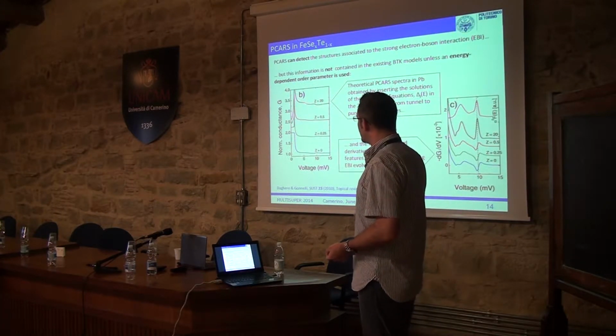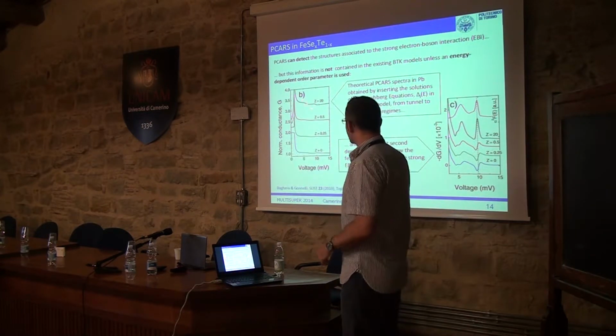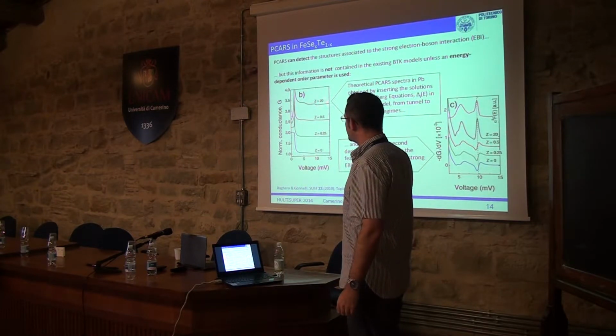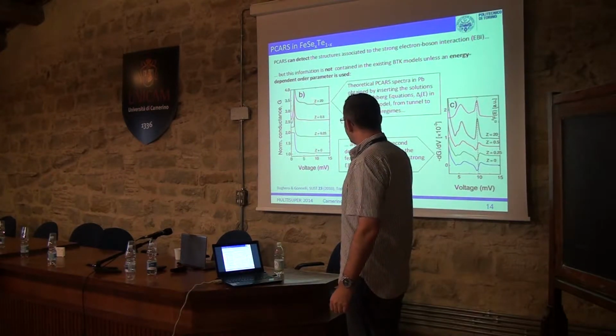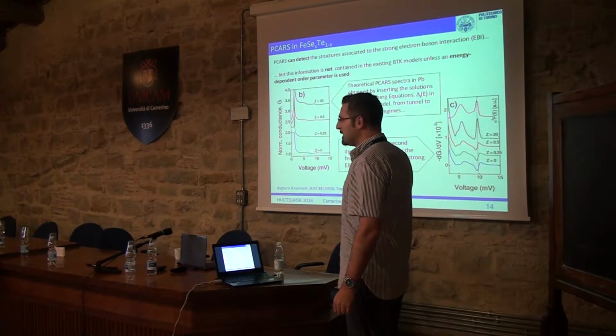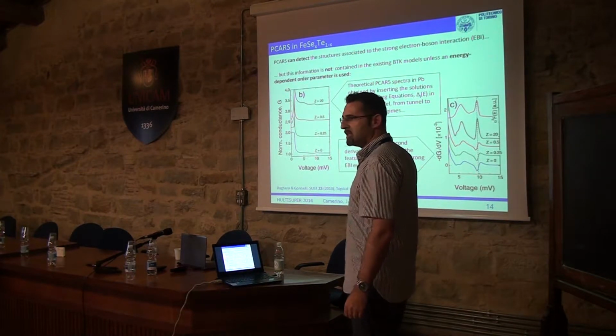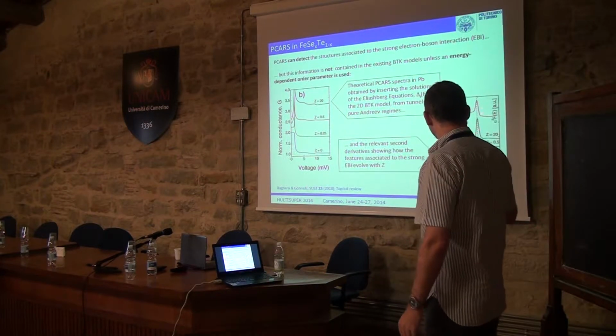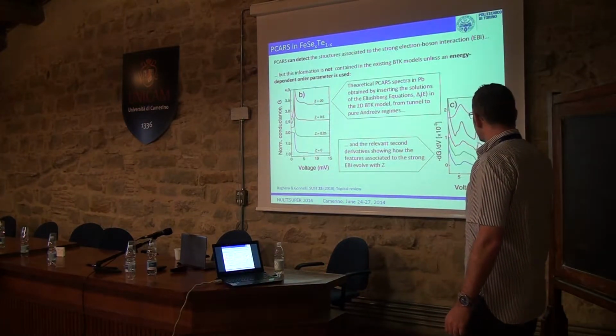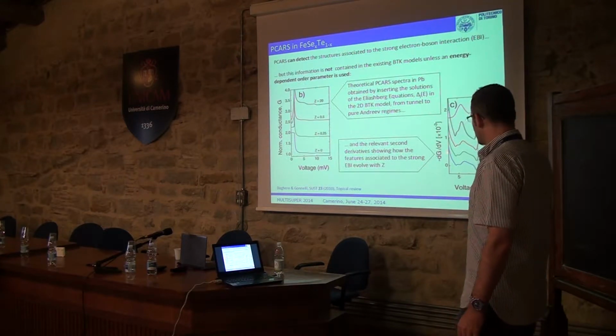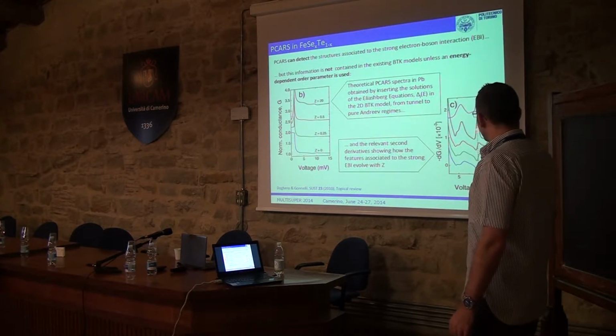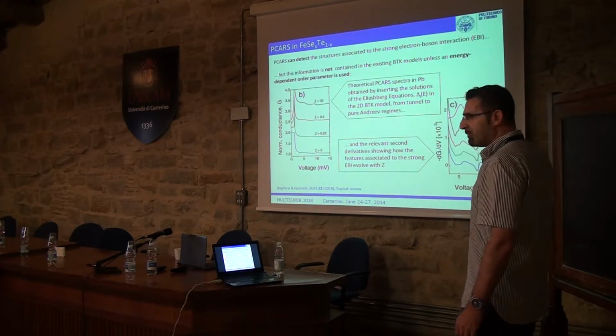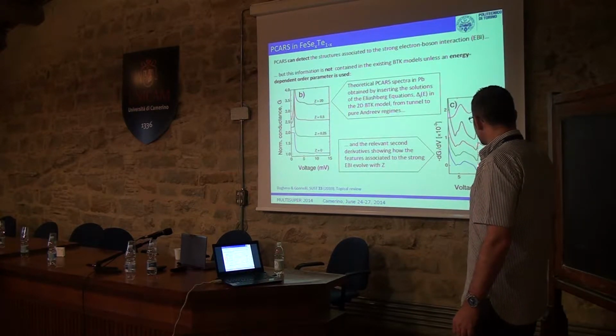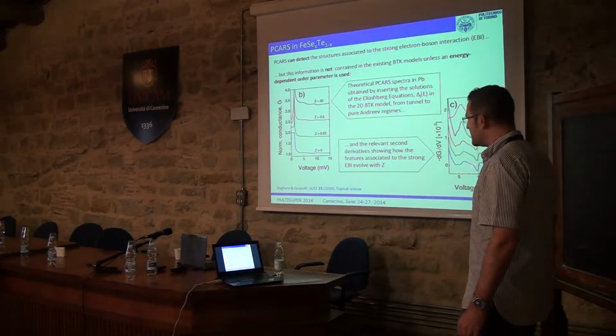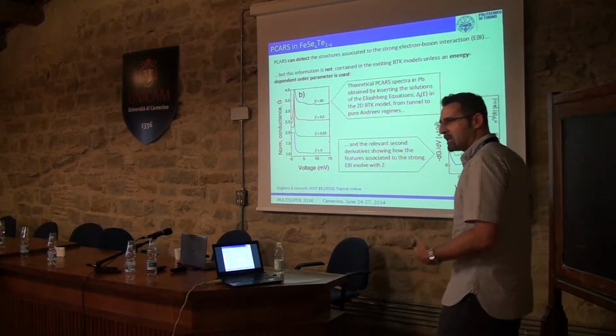For example, this is the case of lead. You see these typical, very well-known fluctuations around the BCS density of states. This is Z equal to 20, which means tunneling regime. If you go toward the Andreev reflection regime, Z equal to 0, you see that they still persist. And in the second derivative, there is a perfect correspondence between the peaks in the second derivative of the conductance and the peaks in the α²F. This correspondence is no longer perfectly obeyed in the Andreev reflection regime, but anyway, the structures are there.